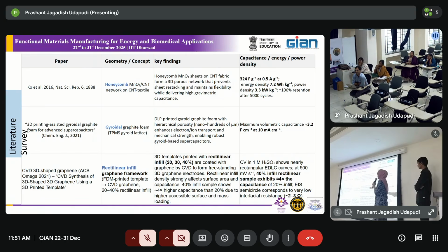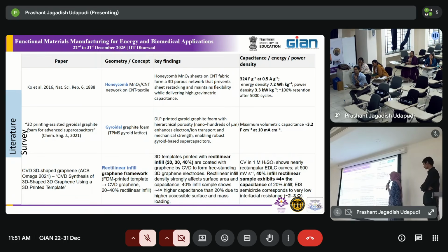And then the gyroidal pattern, they have used the gyroidal pattern in graphite foam. They have used a DLP-based method for printing this, and they have obtained a volumetric capacitance of around 3.2 farad per centimeter. And another one is rectilinear infill. They have used rectilinear infill with infill percentages of 20, 30, 40 percent, and based on that they controlled it and tried to come up with the results. And it is proven that the 40% infill rectilinear sample exhibits 4 times the capacitance of the 20% infill. So the infill parameter is also very important in this geometry.